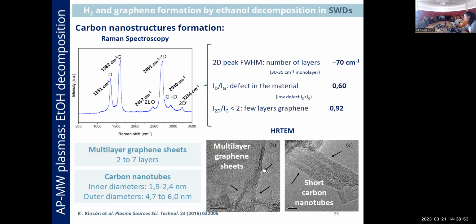We can see here the multi-layer graphene sheets and also the formation of carbon nanotubes. So what we are obtaining when decomposing ethanol with our surfatron, with our surface wave discharges, is a nanocomposite of graphene and carbon nanotubes.